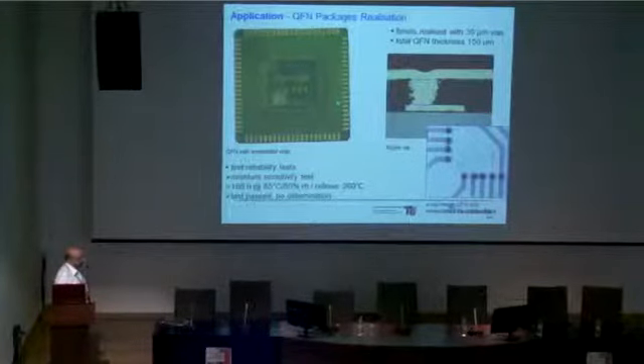We did a lot of very extensive reliability testing. All these probes have passed MSL3, MSL1 levels of reliability, 85% relative humidity, 5 times reflows at lead-free temperatures, and no delamination was observed.